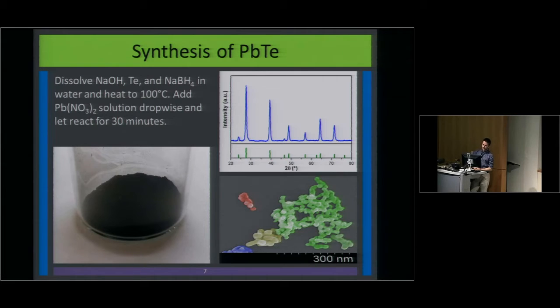And then I did a scanning electron micrograph, which is in the bottom right, of the particles. You can see it's composed of 30 to 40 nanometer, roughly spherical particles. Typically in batteries, smaller is better in terms of performance, and these are pretty small particles. You'll see later we get pretty good performance out of them.